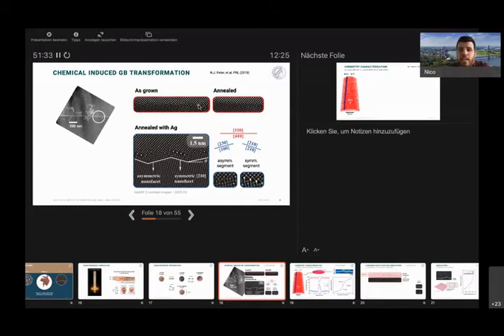What I maybe didn't say clearly enough is that this asymmetric boundary is not too far away from the 210 orientation. You can see from this orientation here to this orientation, this angle is fairly small, right? So the change in inclination is not too big, so there is an energetic cause behind it, rather than strains and things like this. So what we believe is indeed that the boundary takes up silver until a certain point, and then eventually it starts forming these facets to take up even more and then lower the energy further. Does that answer your question?